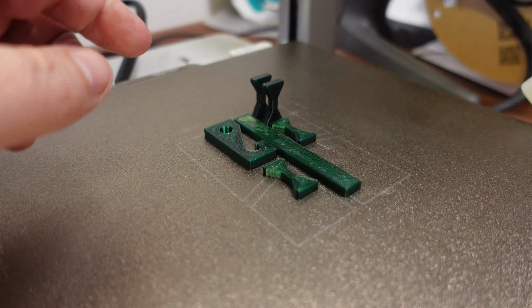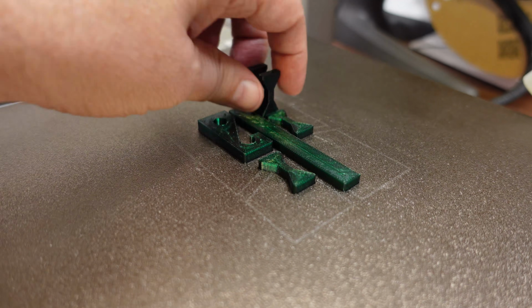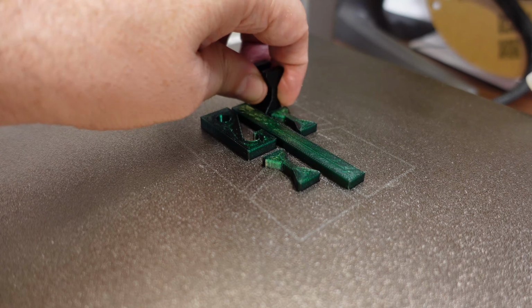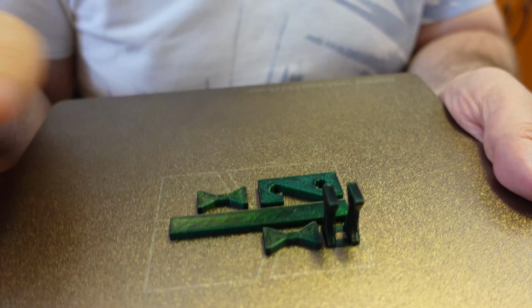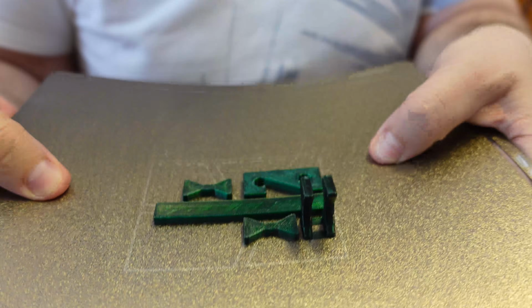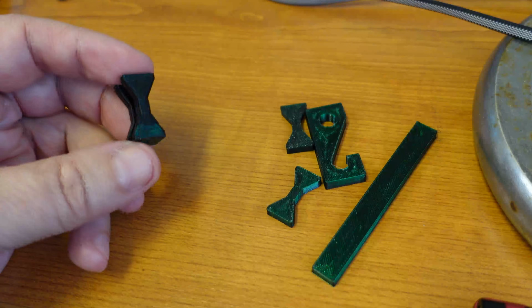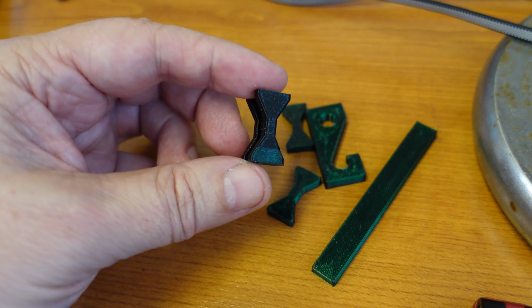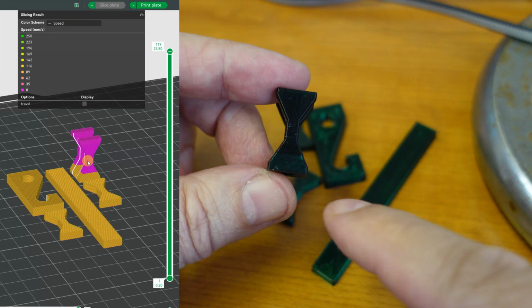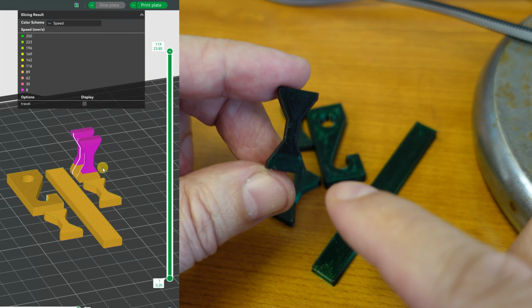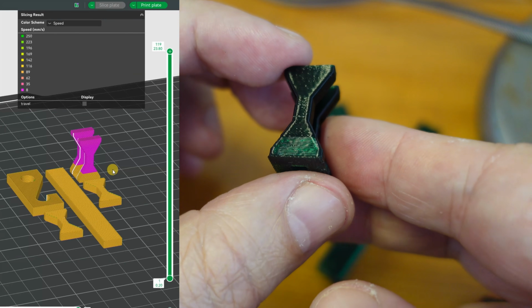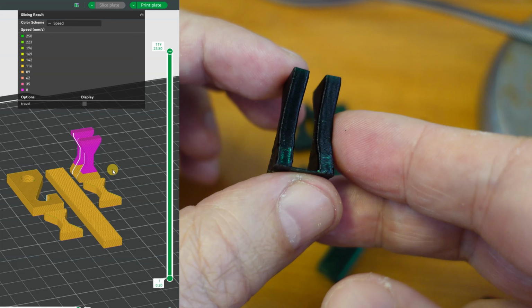It finished a few seconds ago, and I have the feeling that the bed adhesion is good until it's hot. Yes, I have to wait until it cools down. Let it cool down completely. The printing is really nice, but look at this transition here. I hope it's visible on the camera too. And I think the reason for this is that it slowed down significantly after 5 millimeters.